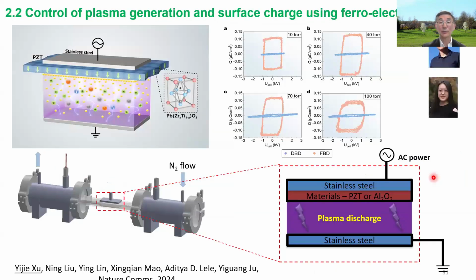The next thing I'll show you is how we can control the plasma further. Sometimes in plasma the electron number density is very low and the electric field is very low. So we try using knowledge of materials, for example, ferroelectric materials. A ferroelectric material is one where, when you apply an electric field, the ions, oxygen ions or metal ions, can move, creating an enormous surface charge. Here I show you an example. This is the surface charge, and this is the voltage you applied to the plasma cell.